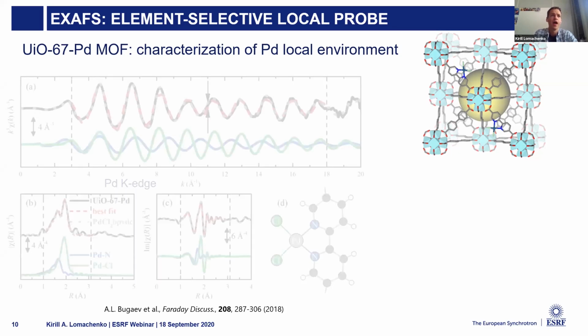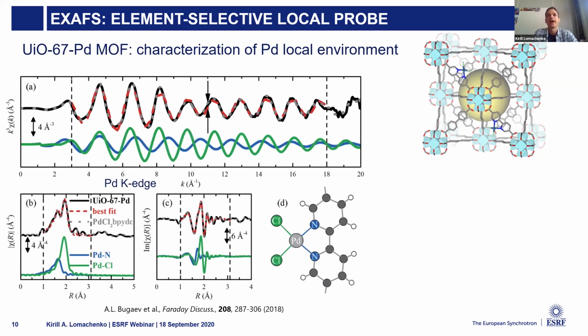What we do is measure EXAFS at the palladium K-edge for the linker and for the MOF. The first thing we see is that the EXAFS spectrum of the MOF is exactly the same as the spectrum of the palladium linker.